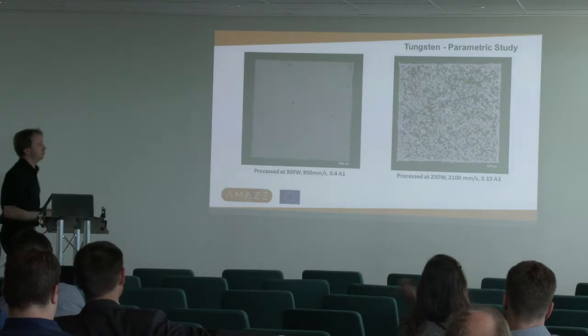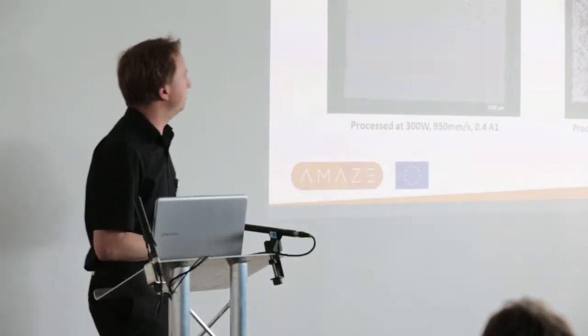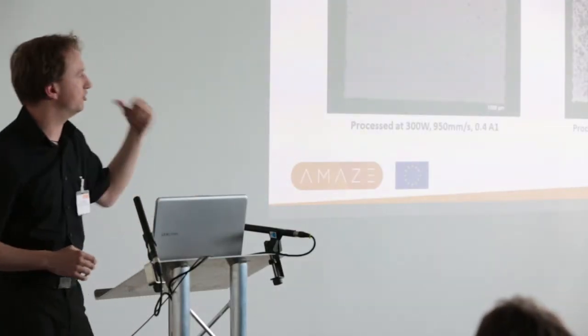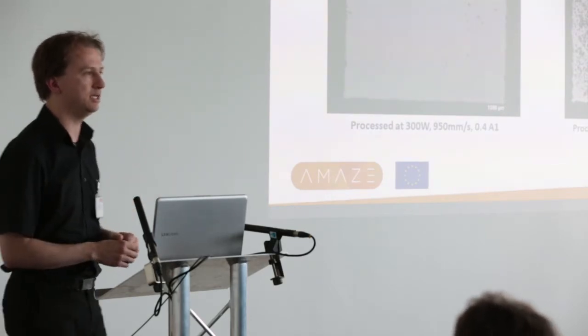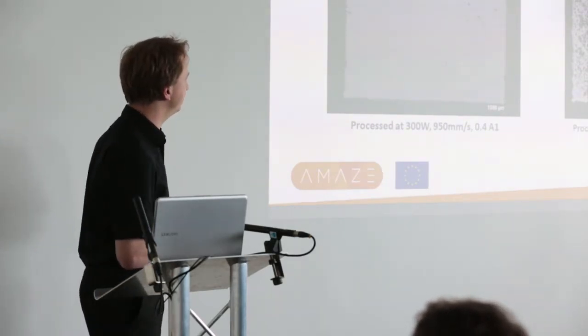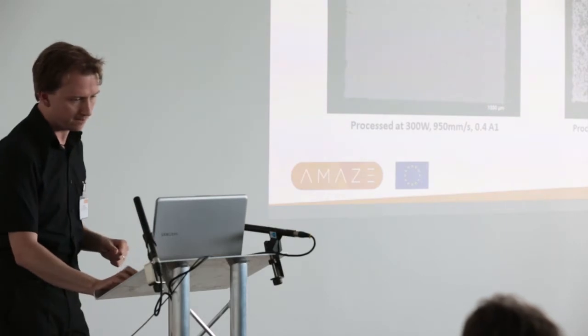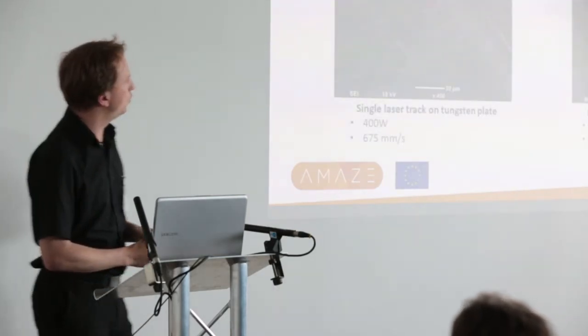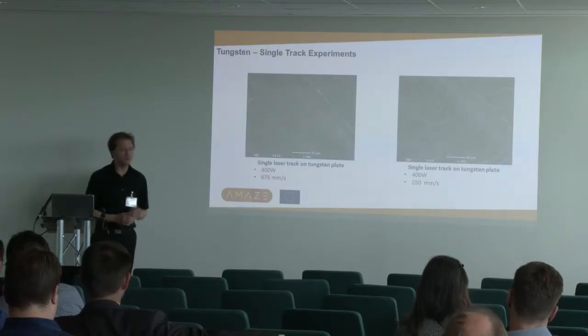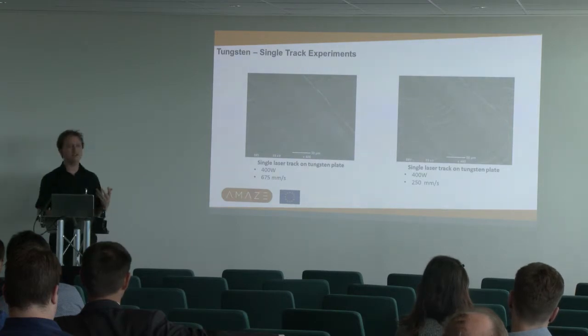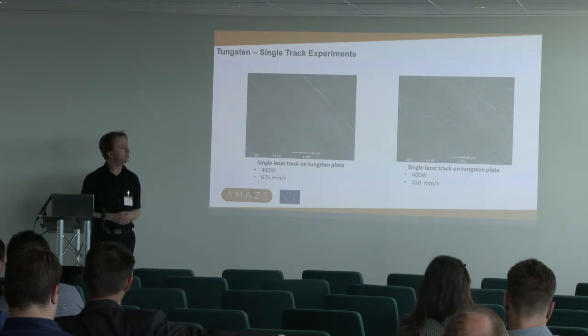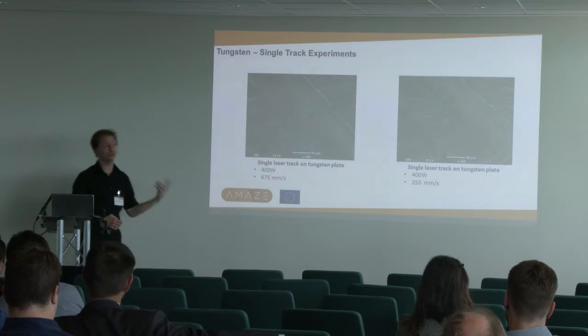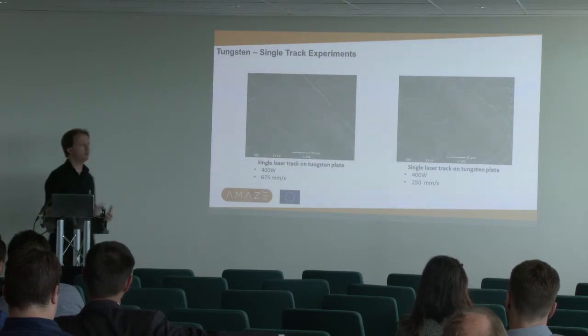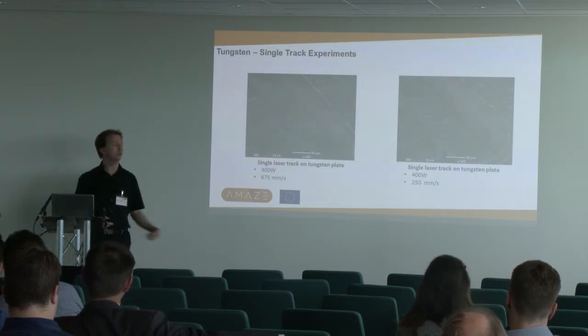Just to give you an idea, these are fairly low magnification optical images, and the image on the left there is our current best, if you like, with tungsten at the moment. Amanda's work is focusing on really trying to get to the root cause of this cracking behavior. She's been doing some work looking at single scan tracks just on tungsten plate to start with, to try and identify processing windows where we're seeing this centerline cracking.